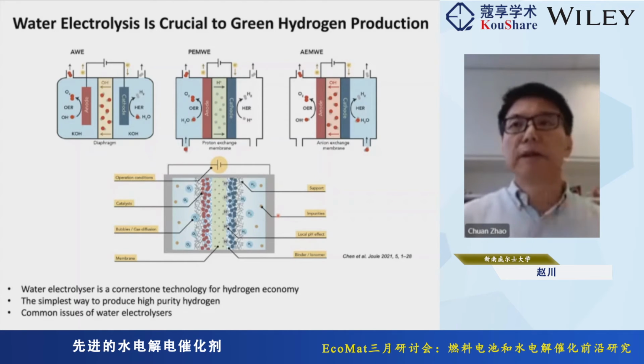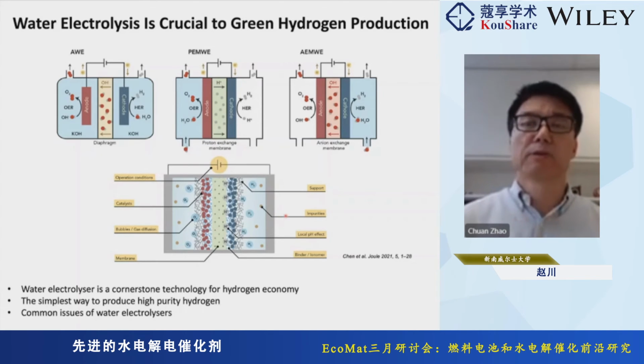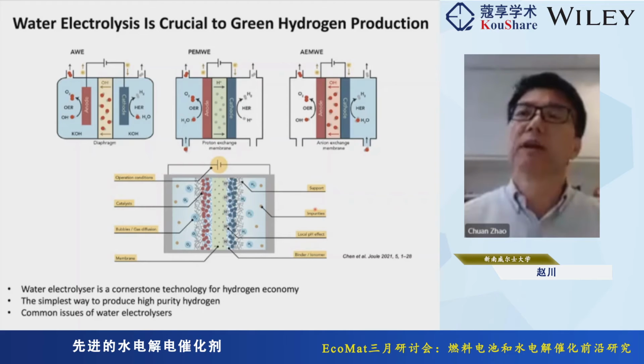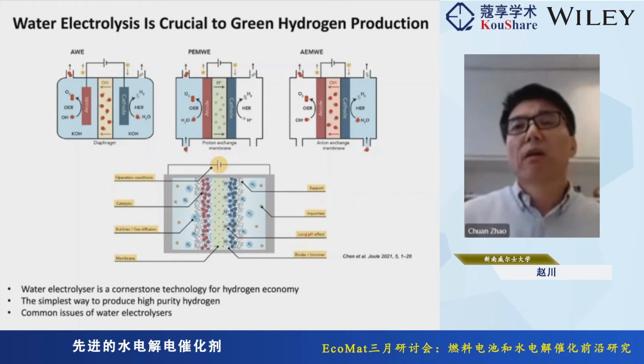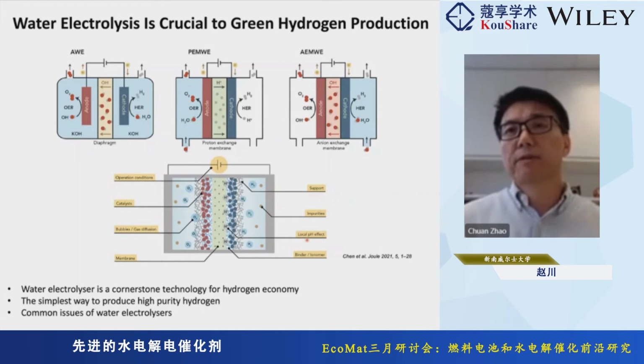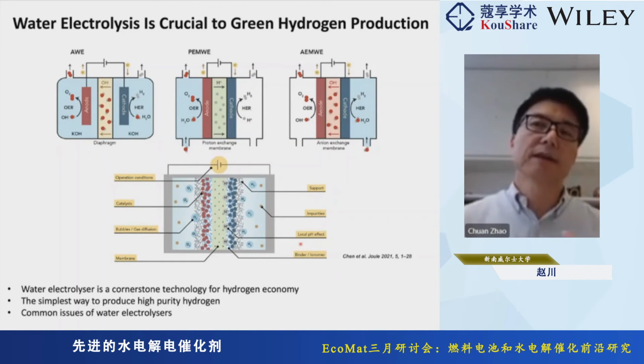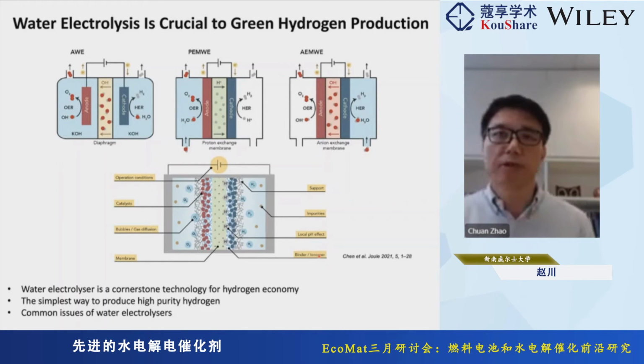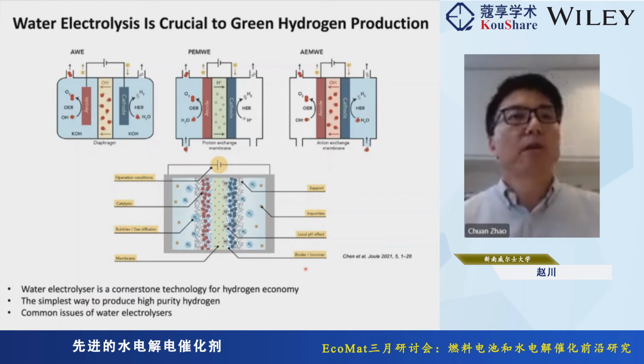It can also introduce significant chlorine reaction, for example, when we do seawater splitting. And also most of the catalysts are designed for a specific pH value, but when you use them in the device, it's completely different. In the microenvironment, local pH will vary significantly from your optimum pH value. And also there are bubble issues which can block your active surface.